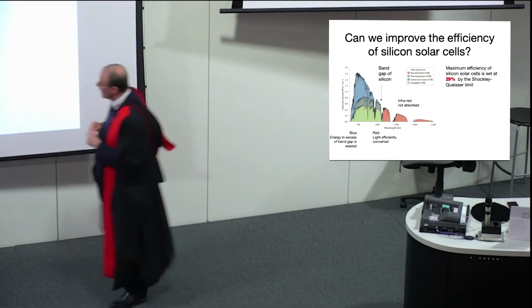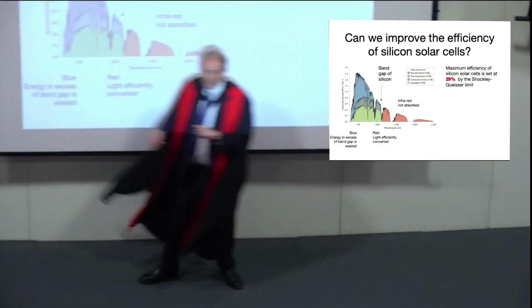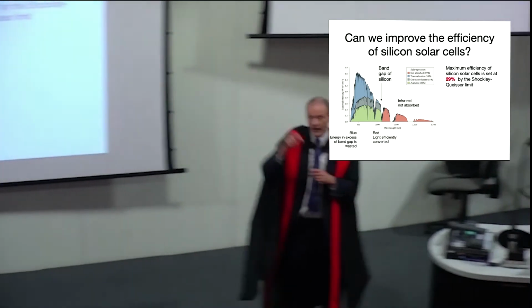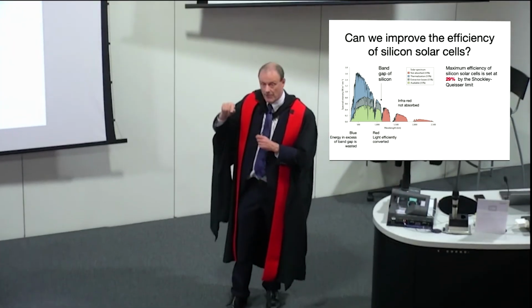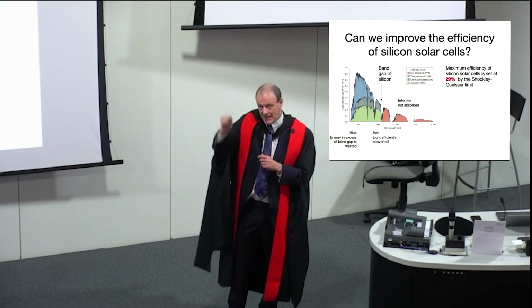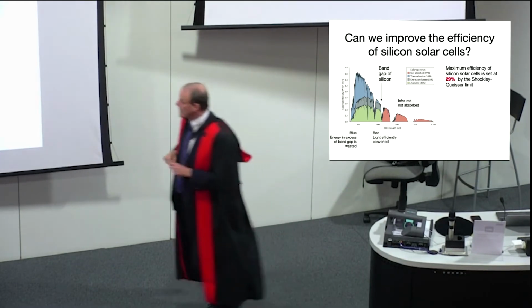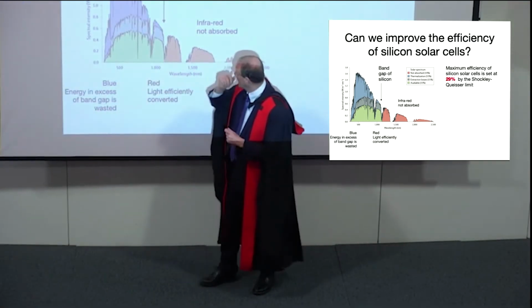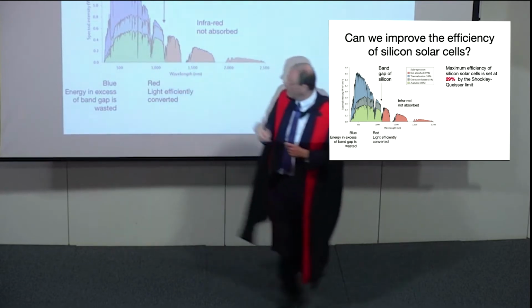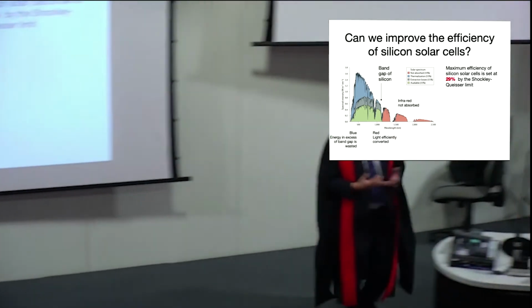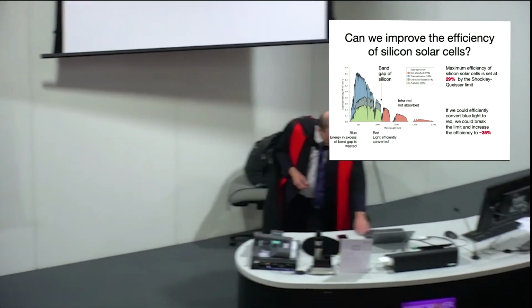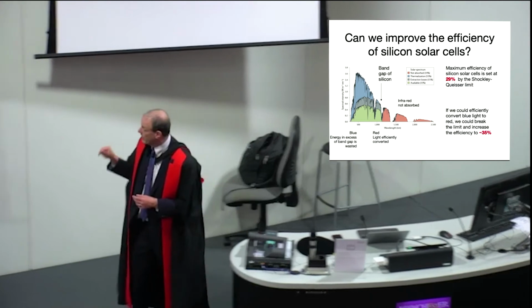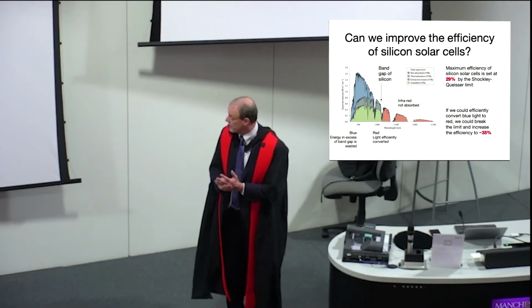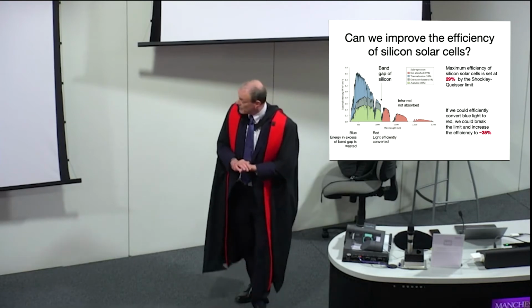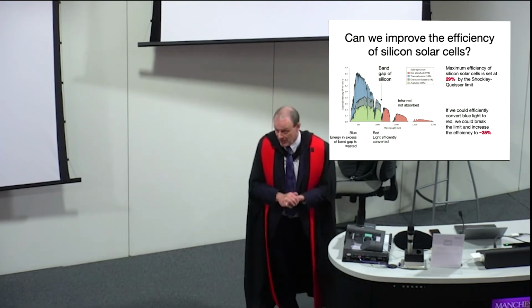It's not absorbed. On the other hand, at the blue end, the energy is absorbed, but then the electron is very high in the conduction band, and there's nothing stopping it just dissipating its energy as it falls back to the band edge. So up here, in the blue light, lots is absorbed, but you lose lots of energy. And so it's only really the energy around the red for silicon where you get efficient absorption. So this suggests, okay, if you could convert blue light to red light, you'd break that limit and you'd increase that efficiency to about 35%, which, 6% on the scale of solar cells, is quite a big deal.